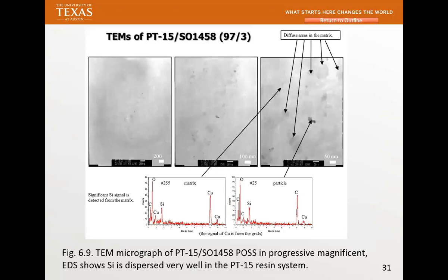Well, what it's showing me is that the POSS I showed you is very large. But with the right technique and the right surface treatment, all the POSS you can see goes from 200, 100 to 50. These little things, when you do EDAX, you can see are truly SiO2, because that is the signature of POSS. So that shows you this little thing is about 50 nanometers. And when you take the EDAX right in the matrix, you could also see SiO in there. So that means you have molecular dispersion, your POSS goes back from this size to nano size. That's what I call very good dispersion.